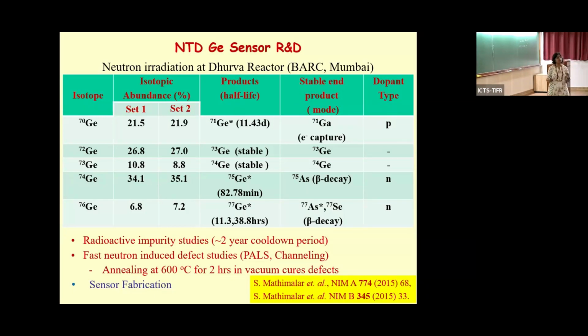You take a piece of a sample which you want, go and put it in a reactor, and we want to have a low background. It doesn't come out clean. It will come out dirty because there are low energy neutrons, thermal neutrons, high energy neutrons, everything. So you have to get rid of all the undesired things that happened. The first thing we do is bring out a sample and do radioactive purity studies, and we had to estimate a cool down period of 2 years which comes in for these samples. Plus there will be fast neutron induced defects, because the germanium crystal also has to be good to be able to get that consistent R variation.